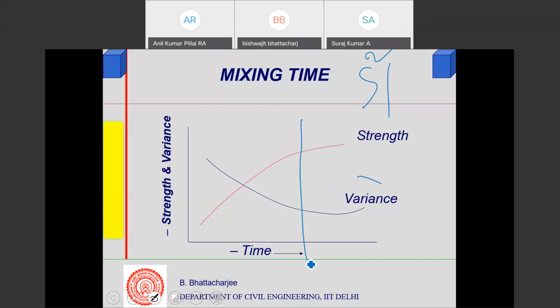Ready mixed concrete plant. Site mixed concrete cannot be as good quality-wise. Quality control cannot be as good. In fact, many of the developed countries use about 70% of their cement through the RMC route. In India, I'm not very sure, it was about 5-6%, more than that. It may have picked up to 7%, let's say, mechanized, but otherwise it is still quite a bit non-mechanized. And there these problems can come very regularly, where nobody bothers. But RMC plant can be used.